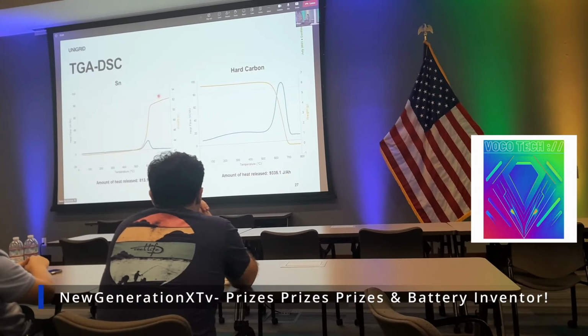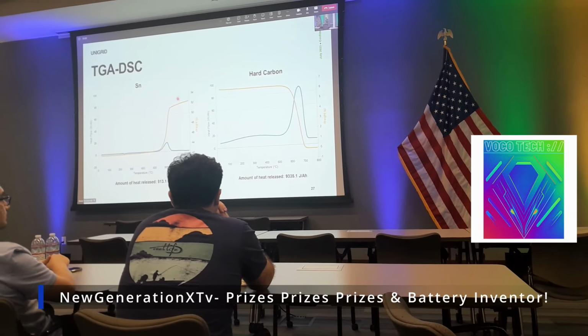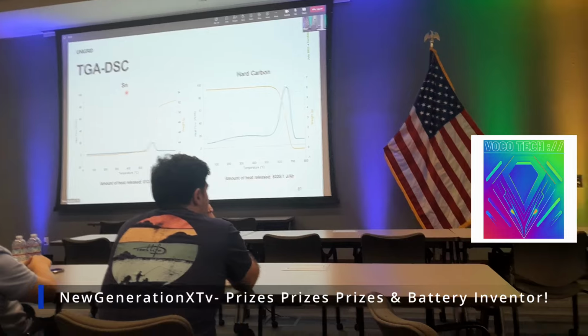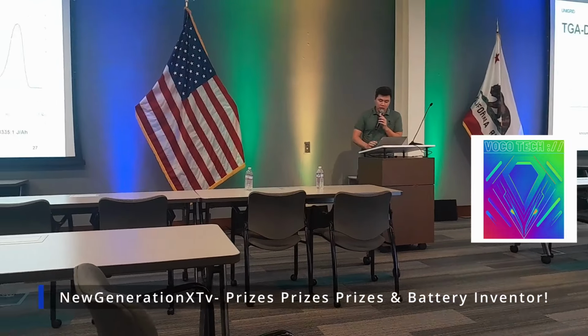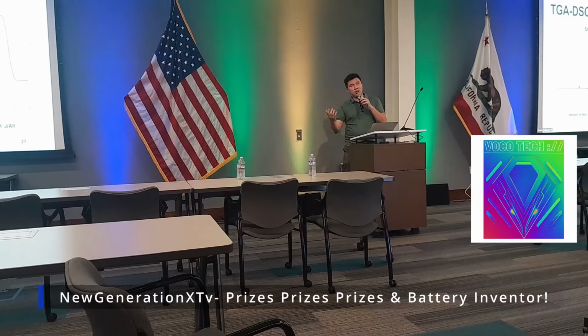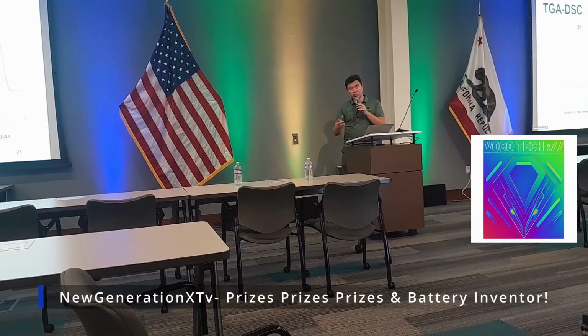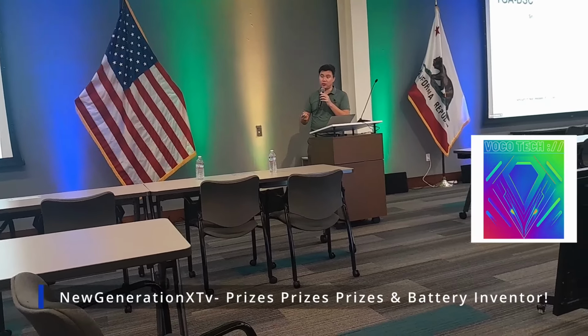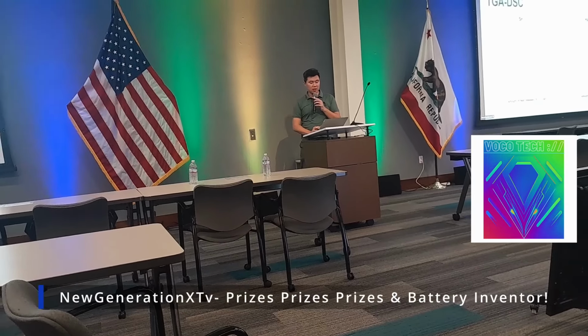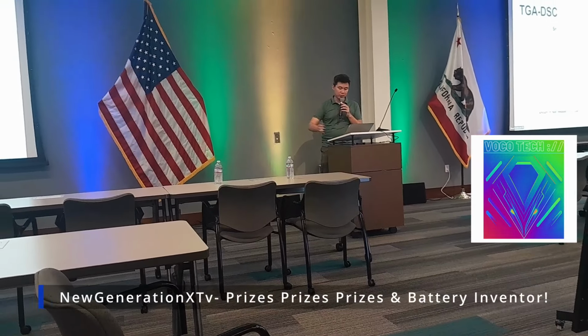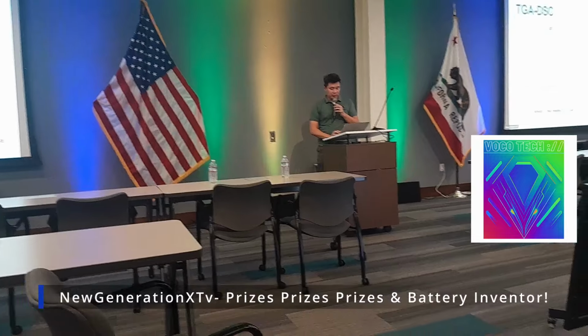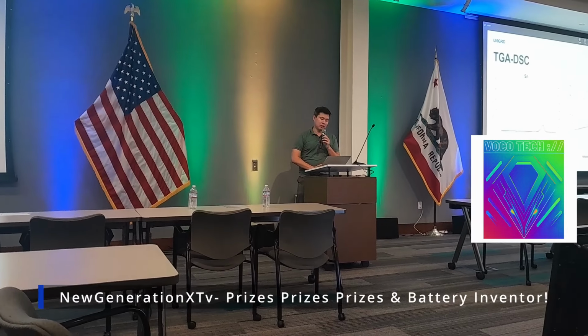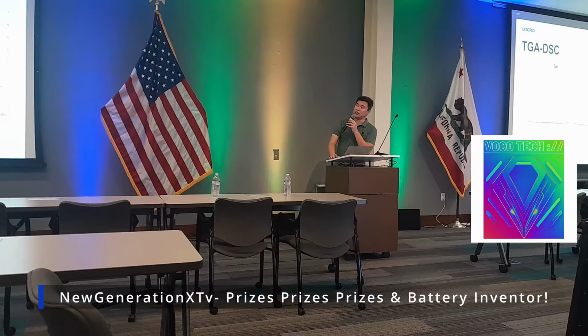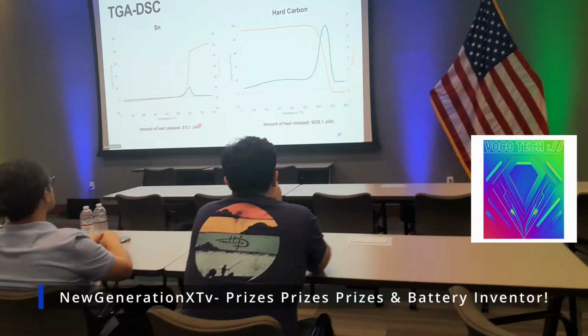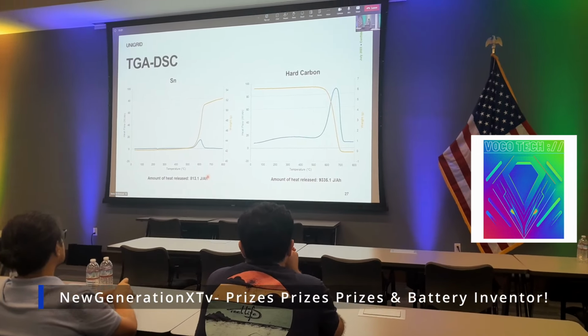So the reason why our technology is a lot safer is due to the intrinsic properties of the material we use. Because we use a tin anode. Tin is a metal, right? A metal doesn't burn. Metal is not fuel. When we heat tin up, it melts, eventually oxidizes. But carbon, which is the conventional anode material, is a fuel you can burn. That's why we use it for barbecue. So it releases a lot more heat when things go up, and that's how thermal runaway occurs. For the same amount of capacity stored, carbon releases more than 10 times the amount of energy compared to tin. That's why we're seeing the huge safety improvements when we switch to our materials. It's actually 11 times.